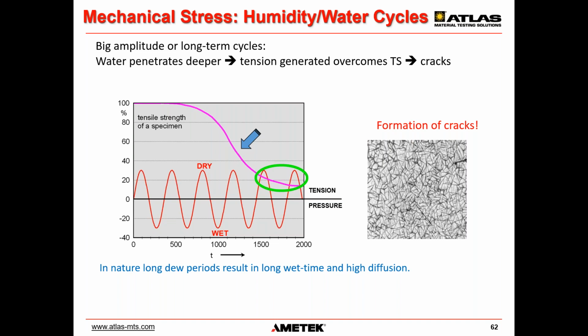to compensate mechanical tensions by swelling and contraction in the rubbery state above the glass transition temperature, which also avoids cracks. Modern 2K PUR systems are very good in this respect. Plus, acid-resistant PUR groups avoid damage by acid rain.